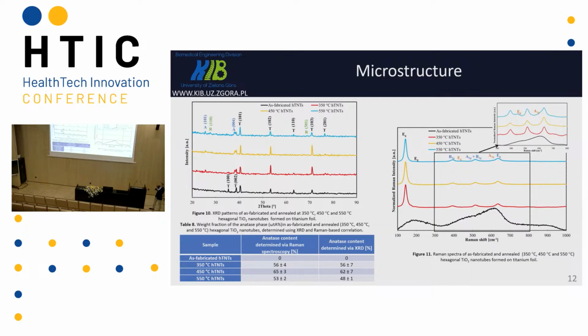So, only the main conclusion. Generally, after annealing in an inert atmosphere in argon for 3 hours at temperatures of 350 and 450, using XRD and Raman spectroscopy, we obtain the concentration of anatase phase. Generally, anatase phase is dedicated to, or preferable for, implant application. And when we use a higher temperature, as we expected, we obtained a mixture of anatase and rutile.